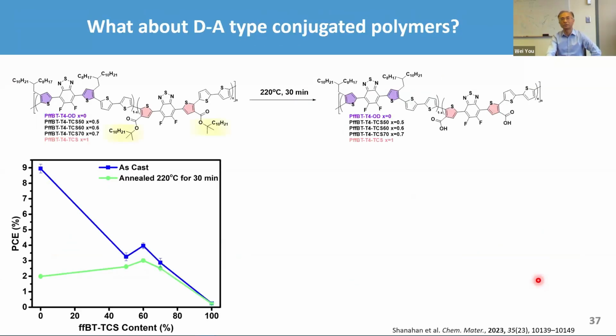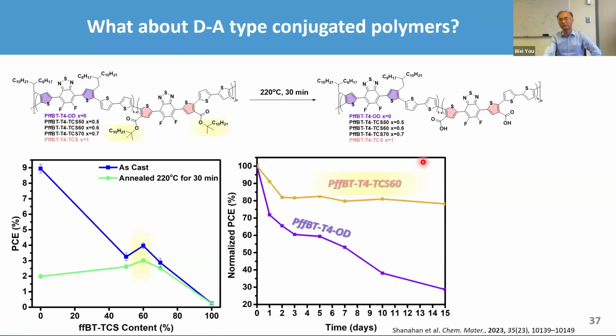We're applying this approach to some other donor-acceptor polymers. The same thing happens if you decorate about 60%, 0.6, which means TCS 60, thermal cleavable side chain 60. With this particular polymer, you can get a very stable solar cell. But the problem again is that your efficiency is not very high. It's only about 3 or 4%.